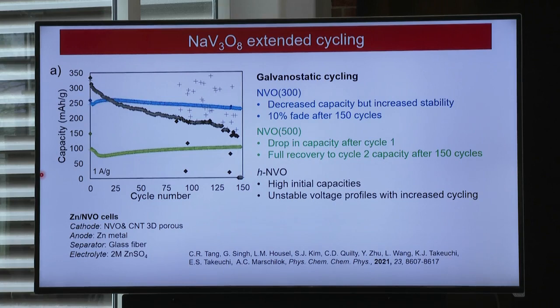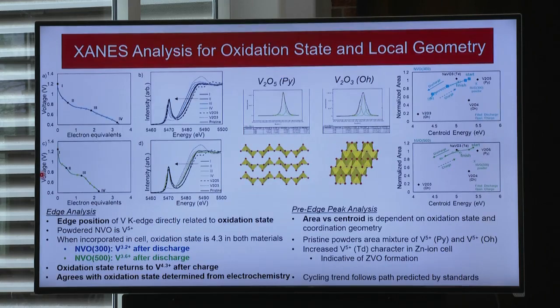And interestingly, the compromised material was the NVO(300), where we were able to start out with relatively high capacity, not quite as high as the hydrated material, but then it would be much more stable than the hydrated material. And so we were interested in understanding why that was the case.